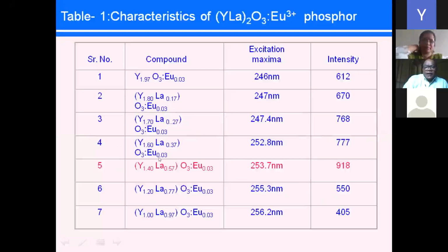Like this, as the contribution of La is increased, at serial number 5 you will see that the excitation spectrum, which is the pink, is at 253.7 nanometer, and the intensity was maximum. Further addition of La has decreased the intensity and the excitation gets shifted. But this is only because 254 is the mercury discharge excitation line, and at 254 nanometer the discharge variations are maximum, and therefore the material should absorb maximum, and that is what is getting reflected in the emission intensity. So it is the improvement in the performance of the material by addition of La and thereby shifting the excitation spectrum.